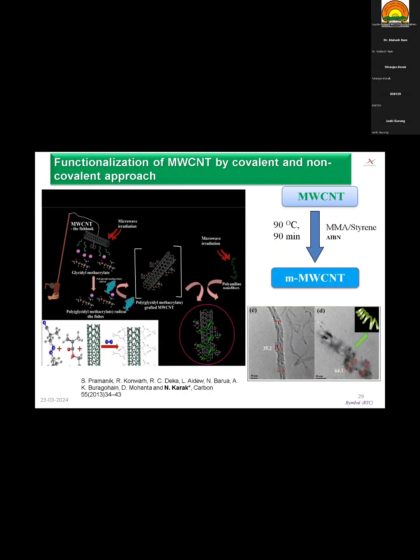Now, multiwalled carbon nanotube is one of the strongest materials and is used largely in different fields. The surface of multiwalled carbon nanotubes aggregates among themselves and is very difficult to interact with other materials, and hence it needs surface modification. Generally, covalent or non-covalent modifications are used. When you do covalent modification, there is a problem that degradation of the tube may occur and the aspect ratio of the nanotube may reduce, which reduces its efficacy. On the other hand, if you do non-covalent modification, the effectiveness of modification will be less, even though the aspect ratio remains the same.